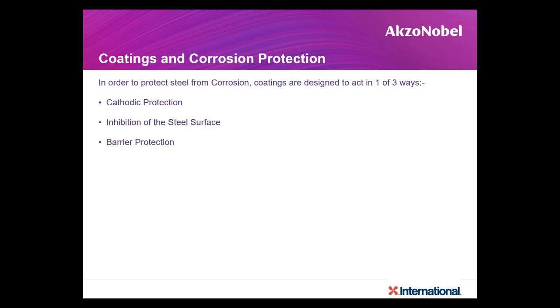Then we have an inhibition process on the surface where specific inhibiting chemicals are added in paint, which will react with the environment and form a layer on the surface which will cover the complete exposed steel area, both the cathode and anode, thereby creating a barrier. That means it doesn't allow further penetration of atmospheric humidity and oxygen inside, protecting the steel. That is inhibitive protection. Then barrier.